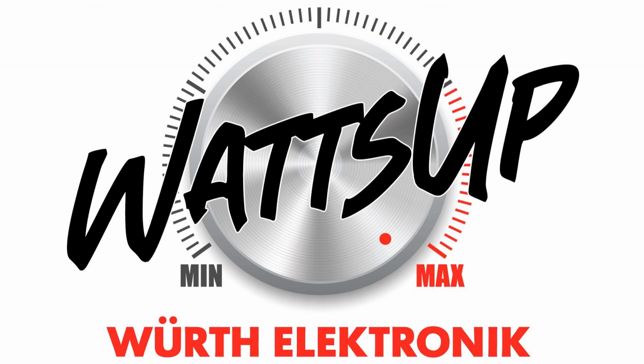For commercial grade products, the core material we use has a maximum operating temperature of 125 degrees Celsius. Because above 125 degrees Celsius, we come close to the Curie temperature and the permeability drops down to 1. So the Curie temperature is where the material starts to lose its magnetic properties. So we must take care of the temperature of operation of our component as well as the current flowing through it.